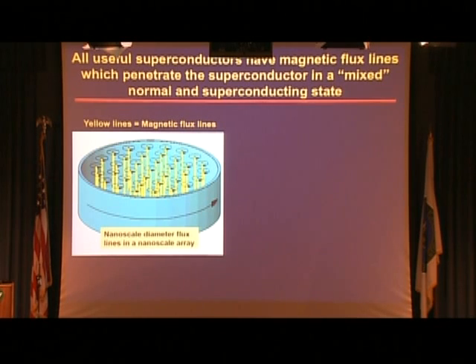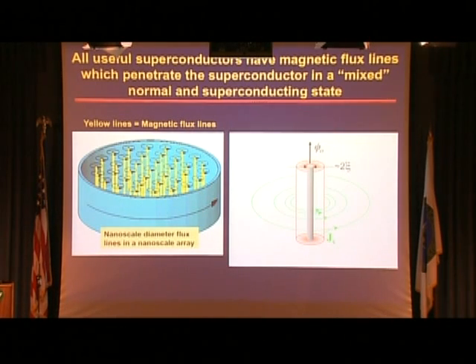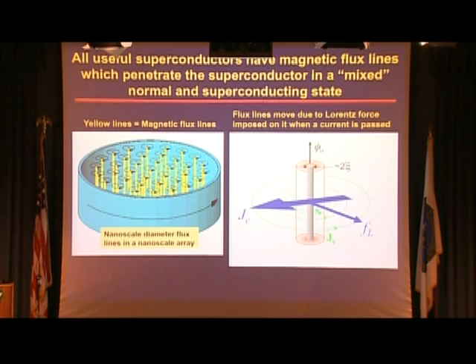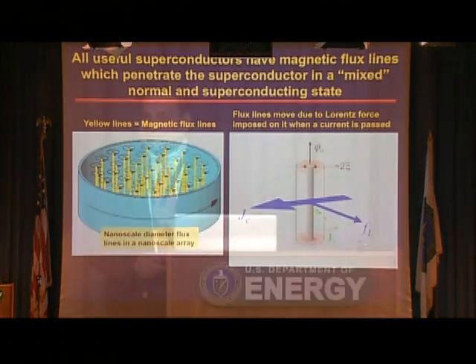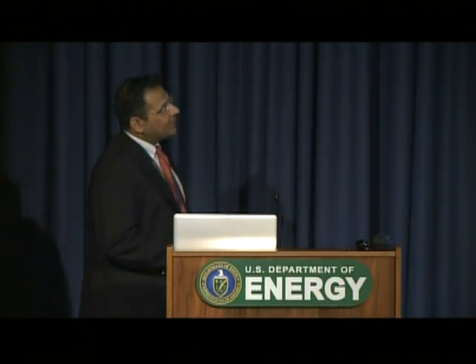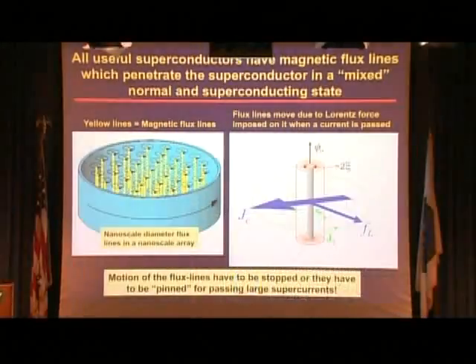And if I were to take one of these flux lines out to the right, and the field is going in this direction, if I now want to pass a current through this wire, indicated by this arrow here, there's a Lorentz force which moves this yellow flux line in the perpendicular direction. And when this flux line moves, it causes resistance, destroys superconductivity. So in order to get good properties, the name of the game is that you need to immobilize these lines so that they cannot move.